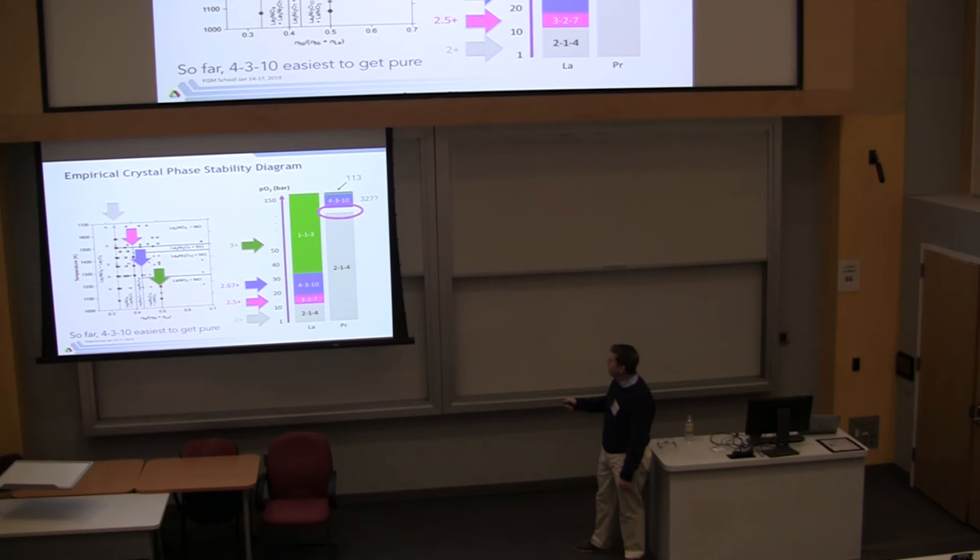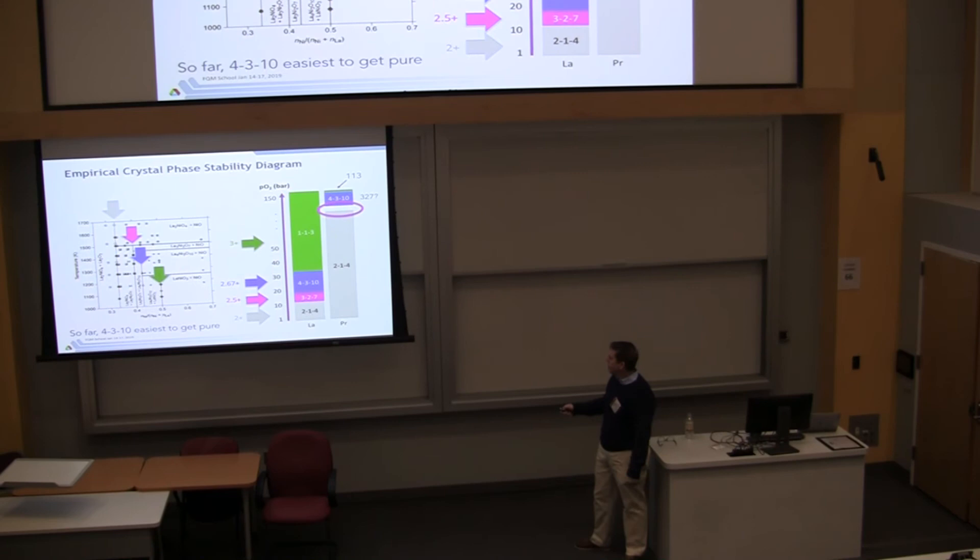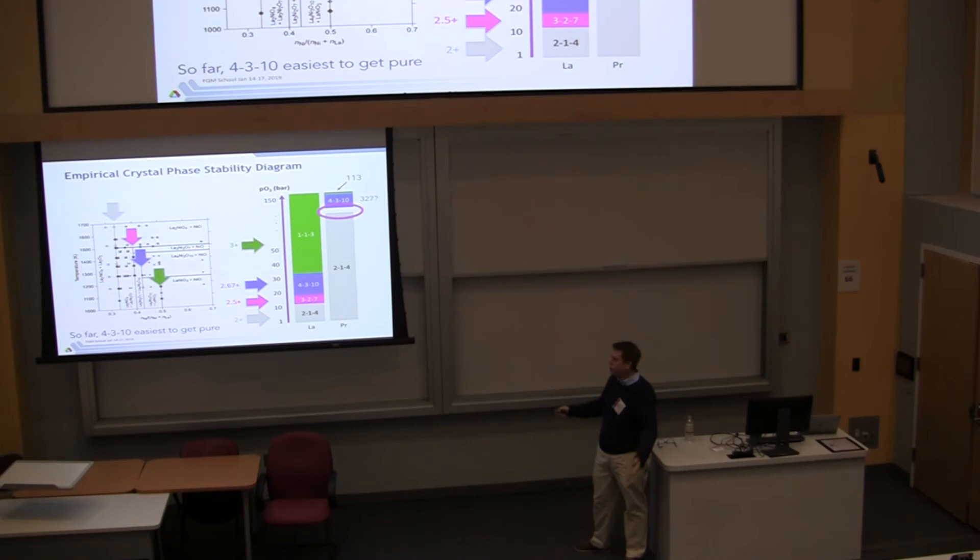And so unlike the charge stripe phases in the single layer material, this seems to be more like maybe a Fermi surface driven effect because we would expect it to be at one third, one third, based on the electron count. But it isn't. It's some very different Q. Finishing up on this in the case of the nickelates. So these are interesting materials because of this phase diagram that's been around for a long time. And what's interesting is the question is what's the nature of this insulator metal transition in the underlying antiferromagnetic ground state.